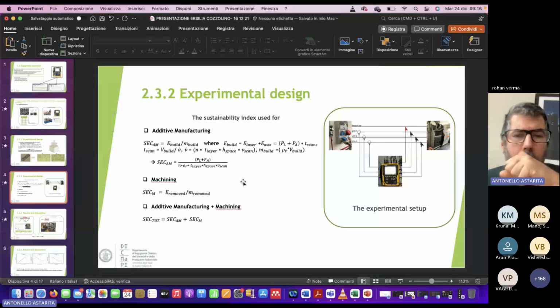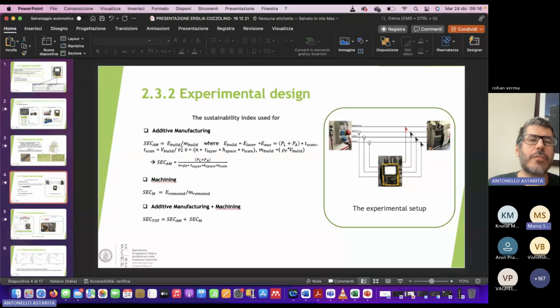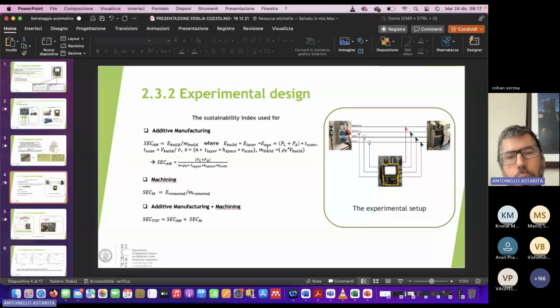Once you measure the energy, you will be able to calculate the specific energy consumption for additive manufacturing. You can write in a first instance that this specific energy consumption is the ratio between the energy required for the whole build and the mass of the samples you printed. But you can also write that the energy required to obtain the build can be calculated as the energy required by the laser plus the energy required by the auxiliary systems, because you have, let me say, a circulating gas pump, you can have a vacuum pump or other equipment, you can have other auxiliary machines. So you can divide the energy that you spent for the whole build into two amounts: the energy required by the laser, which is related to the process parameters, and the energy required by the auxiliary systems, that sometimes is not related to the process parameters, and is only related to the processing time.